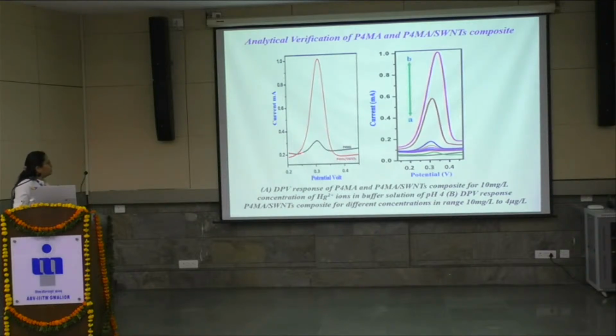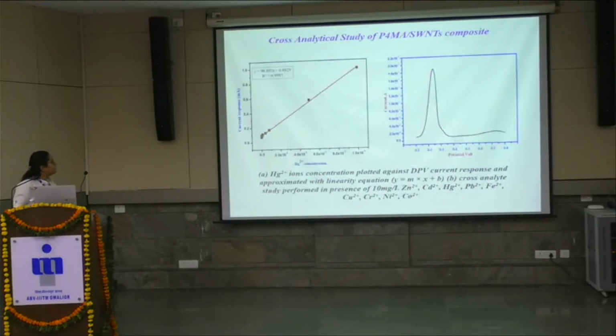First of all, we have explored P4MA to the mercury ions, where it has shown less sensitivity. But once we explored the nanocomposite, it has shown good sensitivity. And later, this P4MA SWNT nanocomposite was explored for different concentrations of mercury ions. The different concentrations were in this range. Now, this is a linearity curve. It has shown good results. Now, this is a selectivity graph, when the nanocomposite was explored for the different cross analytes, so it has shown a great amount of selectivity.